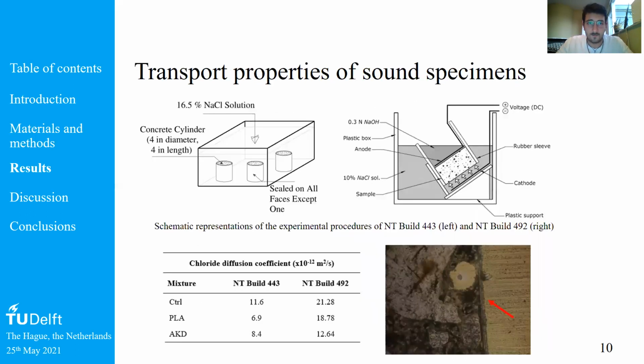Furthermore, we evaluated, briefly, some transport properties of sound samples, so not of cracked samples, the chloride diffusion coefficient, according to the NT Build 443 and 492, for the same mixtures. And we saw that the values for the control series were always much higher than those of the PLA and the AKD, as you can see in the table at the bottom. And that was why we didn't conduct MIP yet on these samples, but we observed precipitation of a thin layer of calcium carbonates at the surface of the sample that might be responsible for the improved transport properties of our material.